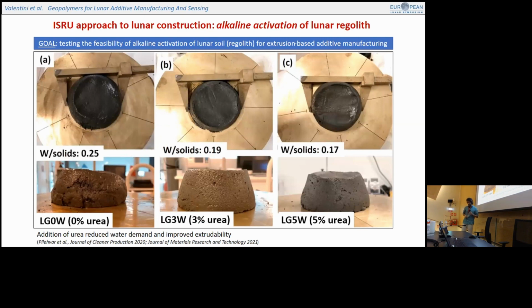Okay, these are some preliminary studies that were carried out in collaboration with the Oslo University in Norway and the European Space Agency, in which we carried out tests by alkali activation of lunar regolith simulants, and we wanted to test the extrudability of these materials. Okay, so what we saw was that the flowability of the material improved when we added small amounts of urea, and the rationale, of course, is that of obtaining the urea by extraction from the urine of the settlers of the moon bases, and also we can show that the demand of water reduced proportionally to the amount of urea added.